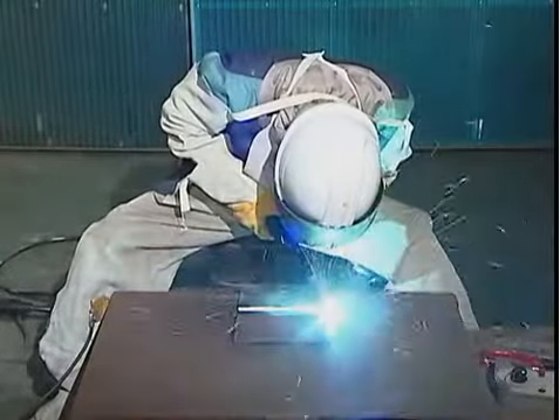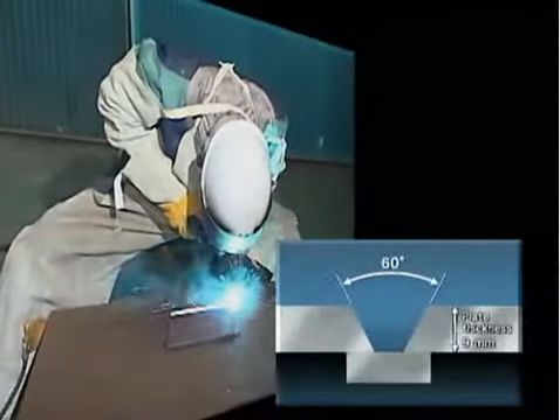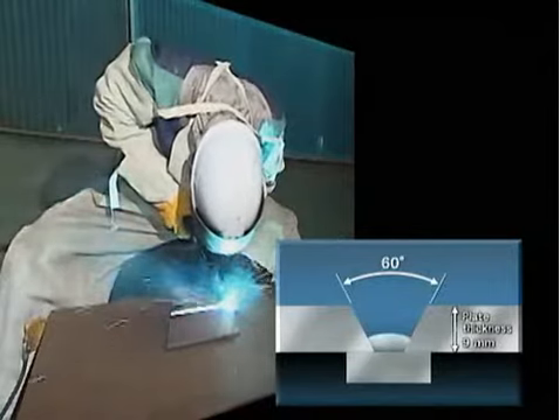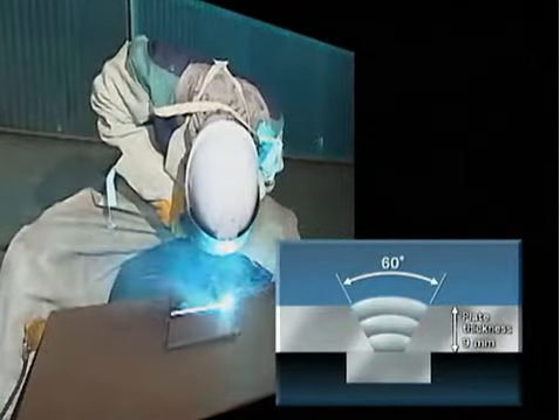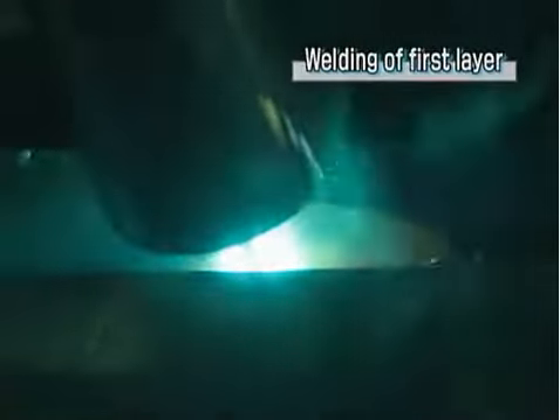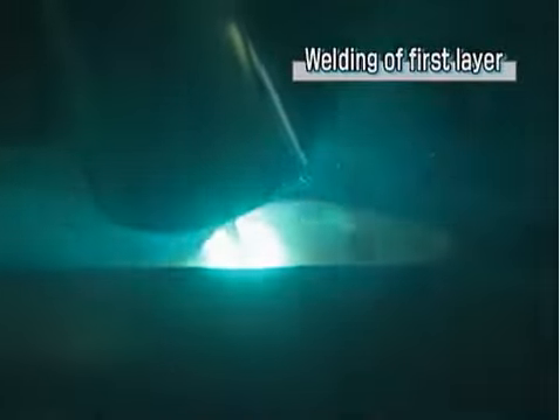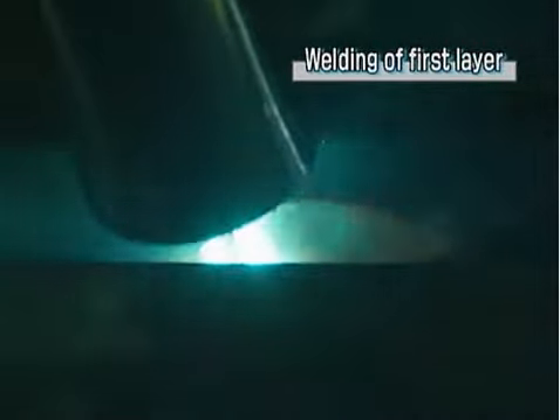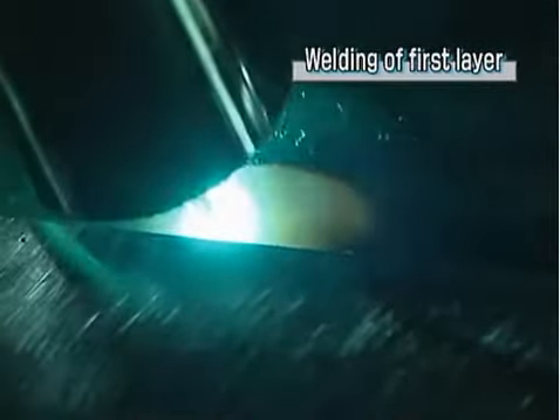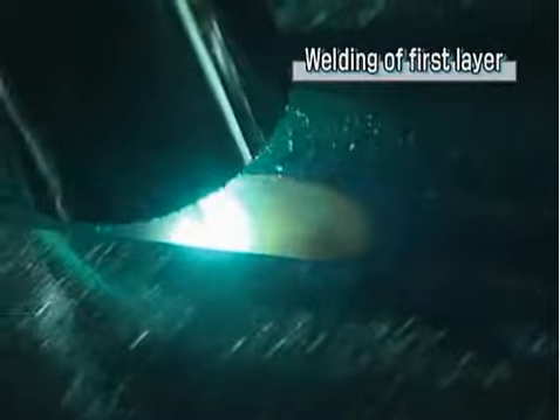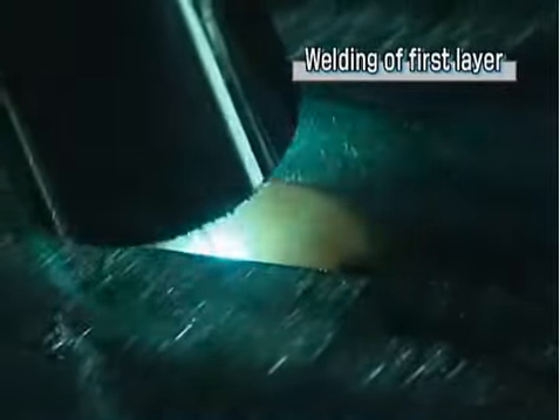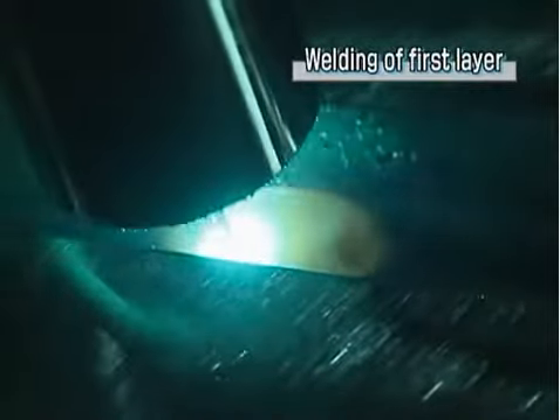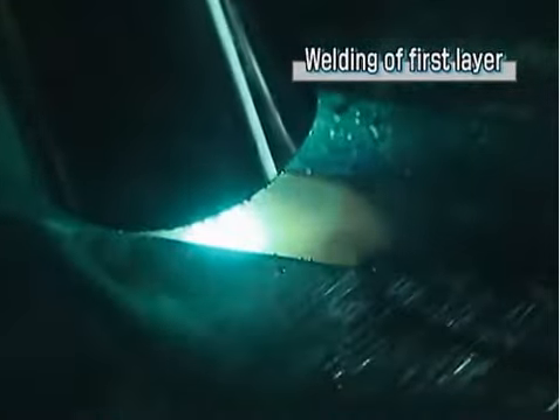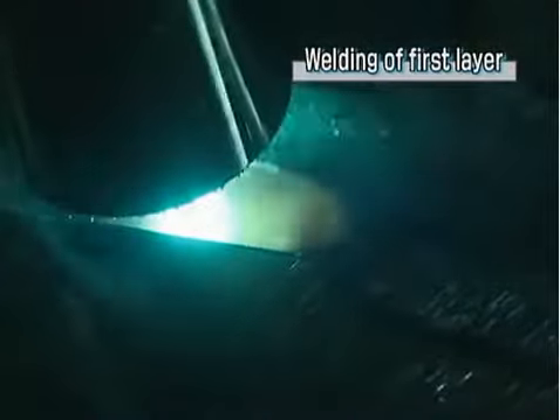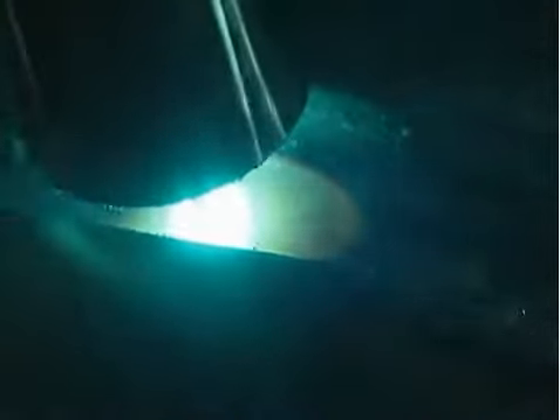The welding will be done in 3 layers with 3 passes. For the first layer, the backward draw method is used to ensure sufficient penetration. When the arc becomes stable, aim for the centre of the groove opening, hold the torch at a reverse 20-degree angle, and weld using a semi-weaving technique with the wire tip zigzagging 2 to 3 millimeters. Aim the wire tip at the groove root and weld pool side and make sure it melts the groove root face well.